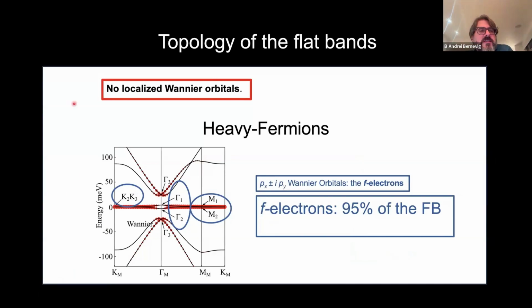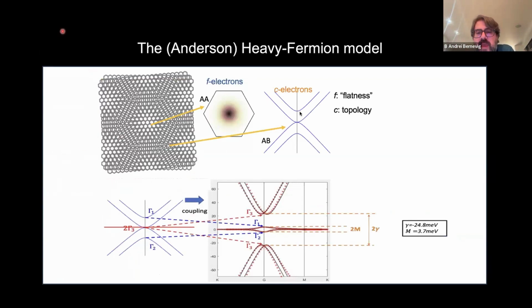And basically, I'm just going to go very fast through here. It turns out that you can think of these 2 flat bands, which in experiments look both localized and delocalized, as being made, 95% of them, out of localized electrons, and these localized electrons sit exactly where those yellow blobs in the STM quantum picture were sitting, plus 5% of the bands made out of delocalized electrons, which look like AB untwisted graphene. So the twisted sample looks like some untwisted delocalized electron, which is gapless at the gamma point, at the center of the Moire Brillouin zone, plus a localized electron.